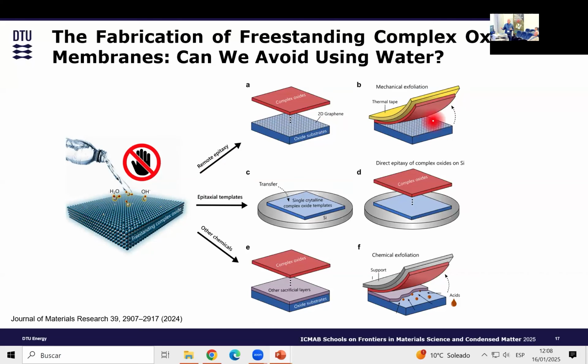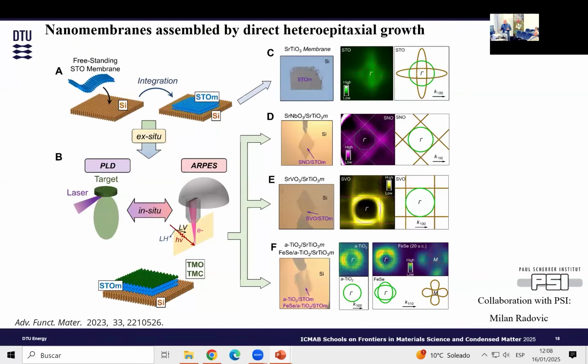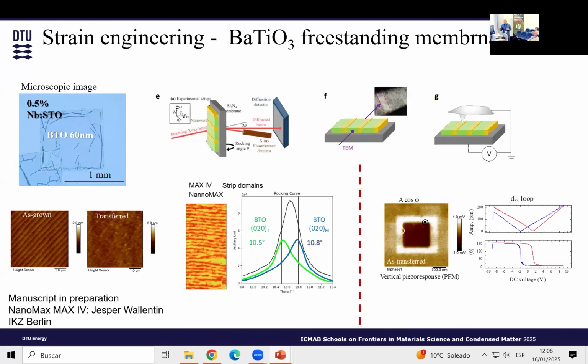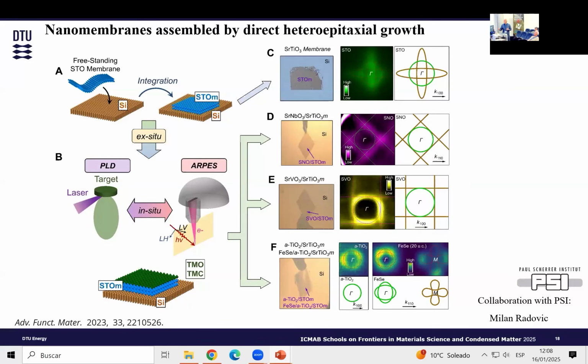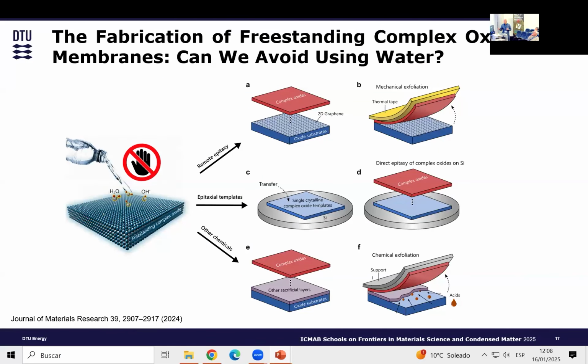The first one is exfoliation using graphene. So this is remote epitaxy. In this way, you don't need to use water. You can also use the lower part, where you use another etchant to etch the material. For example, if you use LSMO, you use another etchant. However, you dilute it in some water, so there is a little bit of water. But there are other etchants, of course, that do not use water. One has to think about it. So you have to find an etchant which does not include water.